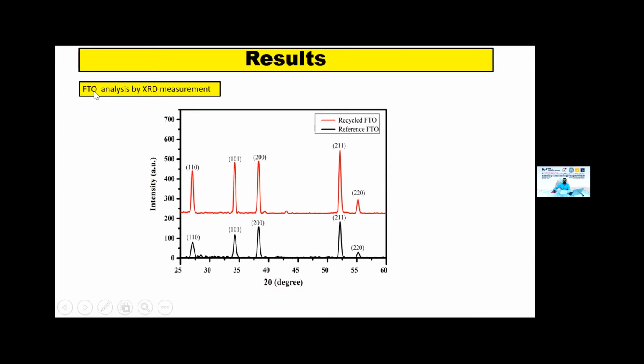We checked the FTO analysis, the structure quality by XRD, and we compared the reference FTO and the recycled FTO. We got the same peaks, so there are no big changes. So we can ensure that the XRD quality of the FTO has no changes, and it can also prove that we can reuse it.